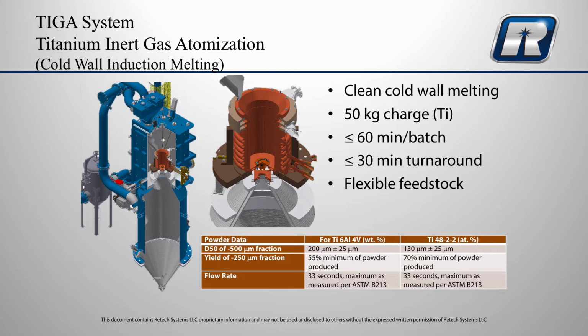But shown on the left, I don't have a pointer here, the atomization tower and the melt chamber are shown on the left with the cold wall induction crucible essentially in the middle of the system. The molten metal comes out of the bottom of the cold wall induction crucible and into the gas atomization die, which is situated at the top of the atomization tower. It's very common. And this system is shown schematically in the upper left-hand corner.